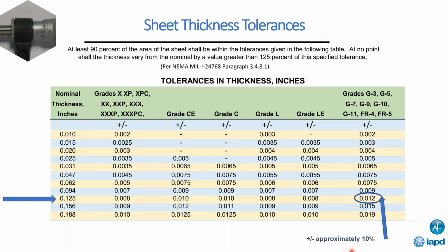So a quick point about the sheet thickness tolerances of our material. Again, all of these thickness tolerances are guided by NEMA, the National Electrical Manufacturers Association. In this example, the tolerance for 1/8 inch FR4 on 125 thick is 0.012, or 12 thousandths. What NEMA says is 90% of that sheet must be within 12 thousandths. NEMA also says that the other 10% can be 125% above that tolerance. So what does that mean?